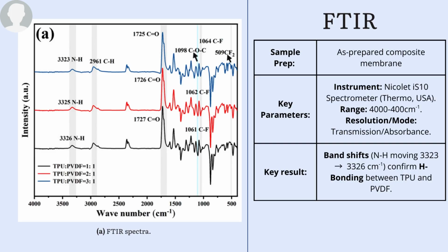Let's begin with FTIR. To evaluate the chemical compatibility of the components, the composite membrane was prepared and tested using a Nicolet iS10 spectrometer. The spectra show the composite membrane of ratio 1:1 for the black line, 2:1 for the red one, and 3:1 for the blue one. Attention should be drawn to the spectra on the left.